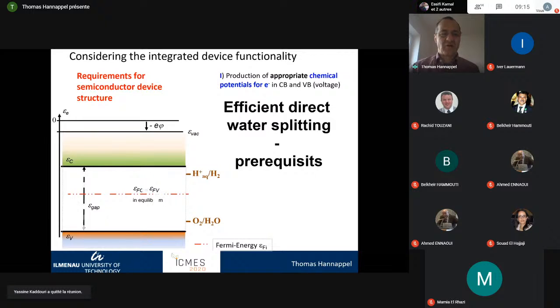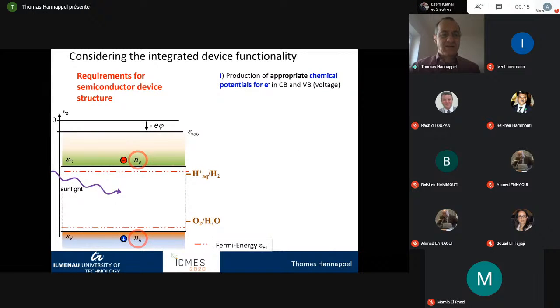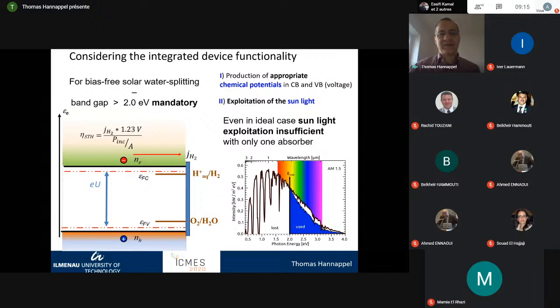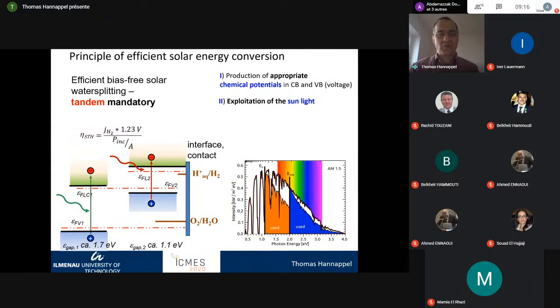If we look again here closer to the semiconductor, the splitting of the Fermi level, the voltage which we are providing is shown here. This depends logarithmically on the charge carrier concentration. This is all educational stuff. I could explain better. Just briefly, we see that we are using such a semiconductor, and compare this to the solar spectrum. We cannot exploit the sunlight efficiently, since there's just not much light in the spectrum left at energies beyond 2 electron volts. So what we do is to create a tandem structure, since this can do both, providing the voltage, which you can see basically here, this splitting, and in addition it can also exploit the solar spectrum, as you can see here on the right hand side.